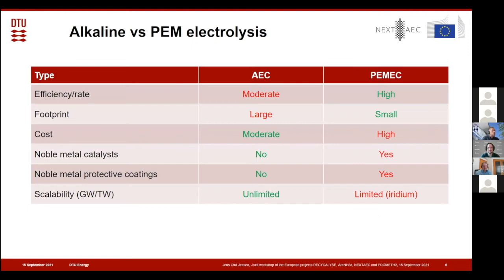So if we compare some of these key properties here, for the alkaline we have the problem of rate capability. I also call it efficiency, but it should be effectiveness. They have to be large in the footprint. That's the drawback. And for the PEM, it is the cost. The actual system cost is not much higher for the PEM because you can do with much less of it. If the rate capability is 3 to 4 times higher, then you can pay 3 to 4 times more for it. So per producing power, they are actually quite comparable. PEM is slightly more expensive, but not so much. But we have these cost issues with the noble metals and the scalability limitation also.